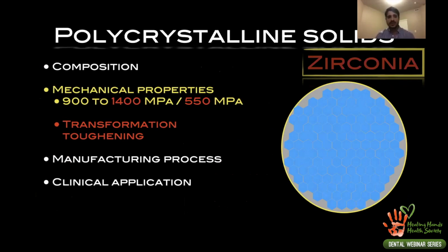The conventional zirconia has a flexural strength of almost 1400 megapascal. Now remember that the lithium disilicate had 450. We're talking about almost 3 times that number. The translucent zirconia has 550, a little bit over the lithium disilicate. So then comes the question, why do we have this difference if they are basically the same material? And the answer is transformation toughening.